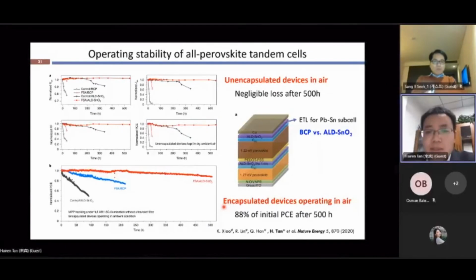And also, if we encapsulate the devices and operate them under the solar simulator for 500 hours, we can still maintain almost 90% of their initial performance if we design the device structure well. I think this is quite a similar phenomenon to the early study of perovskite single junctions. If we do not carefully select the charge transport materials, we can easily degrade the device performance.